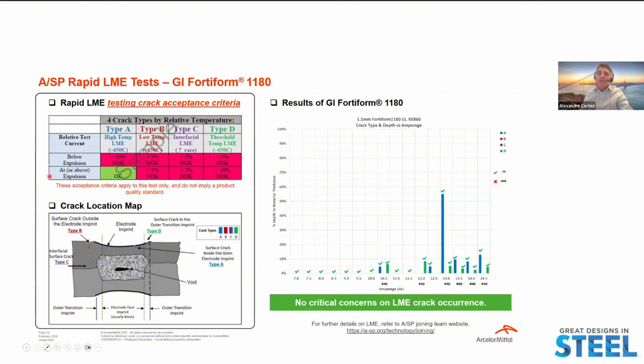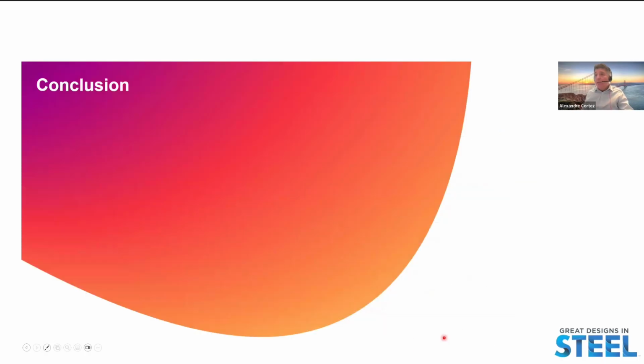And we use this methodology to test our Fortiform GI 1180, and we applied several types of amperage and saw no critical concern on LME crack occurrence in this test methodology applied for this grade. You can see more details about this rapid LME test on this website.